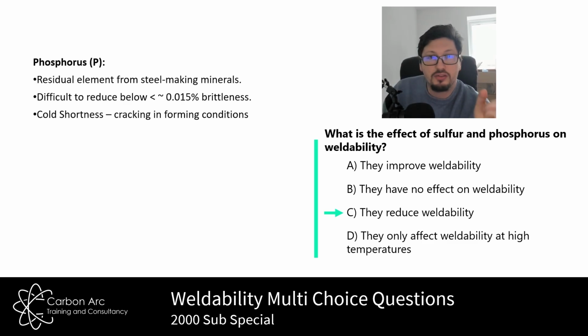I think here I've got phosphorus, okay? It's a residual element, which means we try to get rid of it as much as possible, right? The thing here with phosphorus is once we weld it, it generally produces what we call cold shortness, which is when we take a material and we try and form it, we try and bend it through, say, 90 degrees, and they crack, okay? High phosphorus materials, we don't really want that.